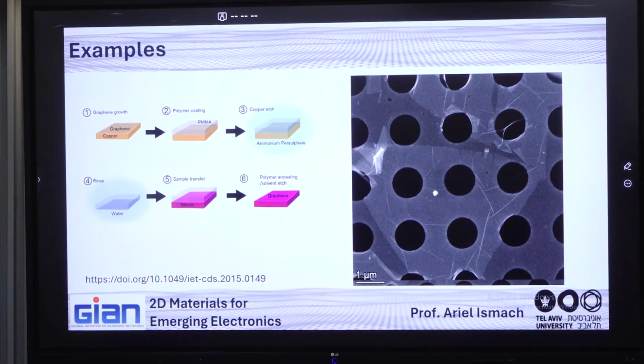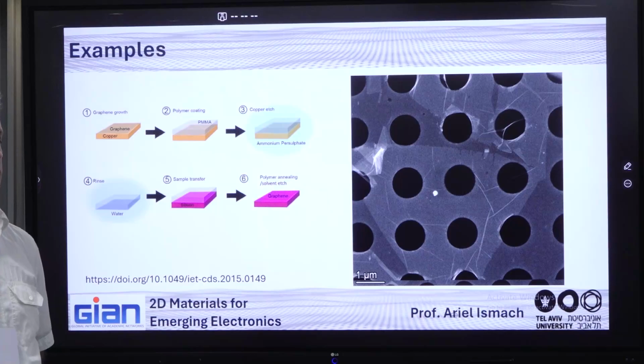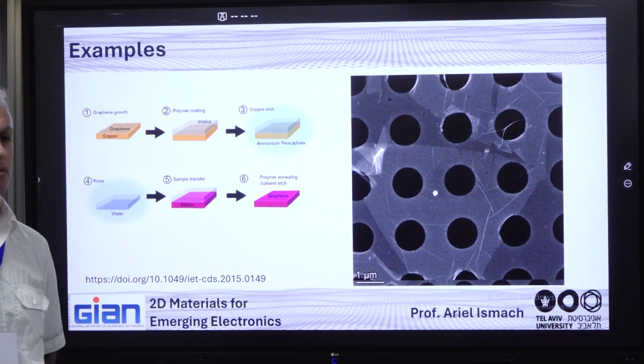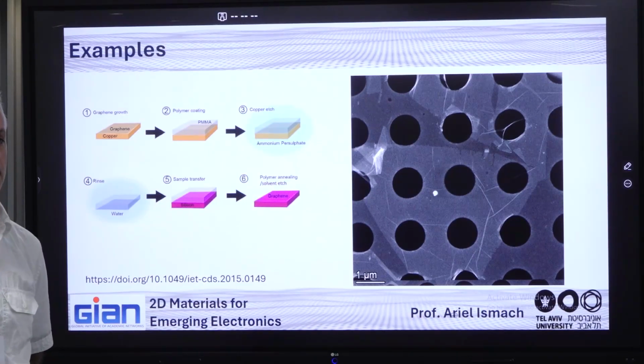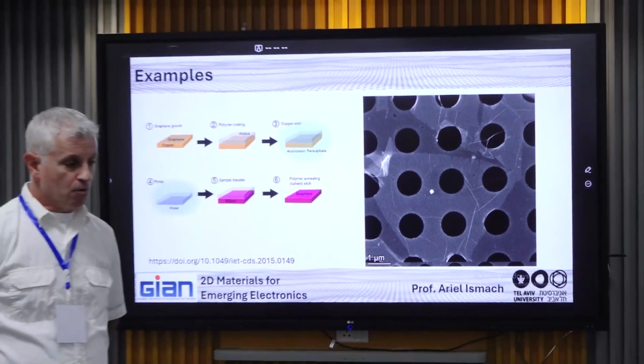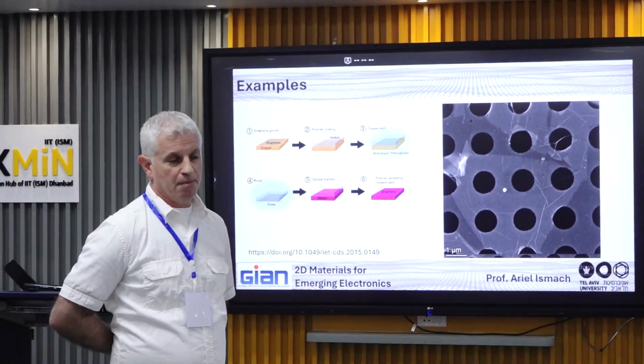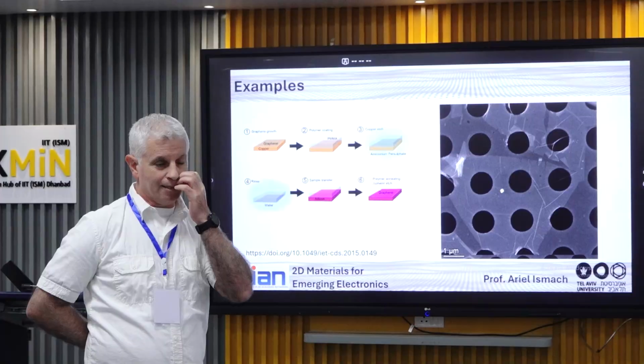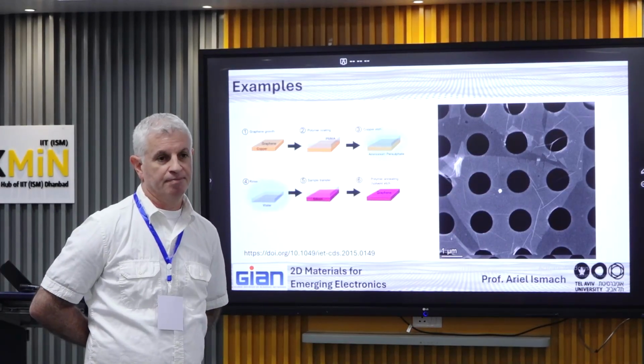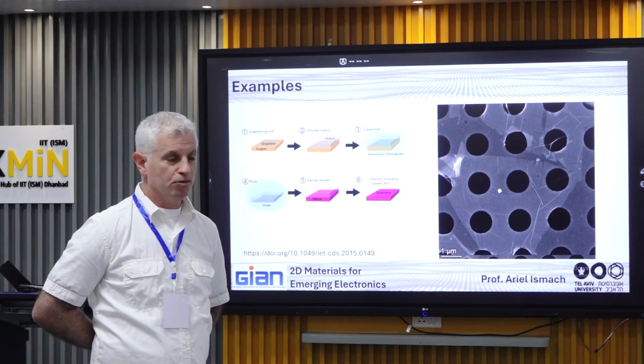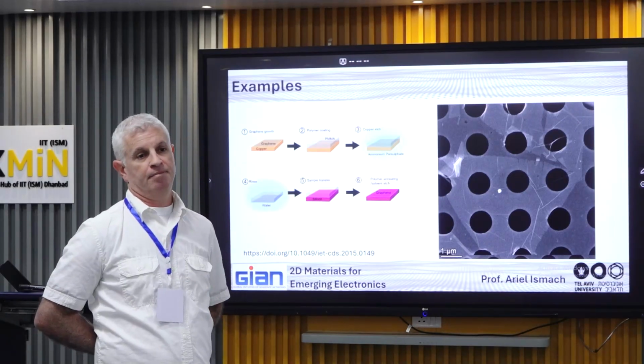So instead of transferring on a grid, suppose we etch the substrate to 1 micrometer. In TEM, typically, is 1 micrometer thickness allowed, right? No. 1 micrometer in TEM is a lot. The substrate thickness is a lot. You can reduce it to maybe a few 0.5 micrometers. There are ways to reduce it, but you will not be able to reduce it enough to get atomic resolution. If you want atomic resolution, you need to suspend it. Suspend.